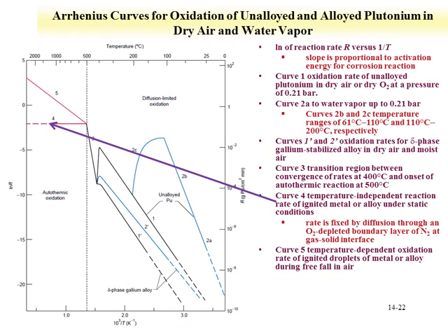And over here, we see that there's a temperature independent rate. As temperature increases, the rate remains constant, and this is for the reaction of burning metal or alloys under static conditions. And then if we do an experiment where you would have droplets of the metal or alloy that were burning during a free fall, you would actually increase the rate with temperature. So the data from this curve demonstrate the role of water in the oxidation and the fact that the alloys are less susceptible to oxidation than plutonium metal.